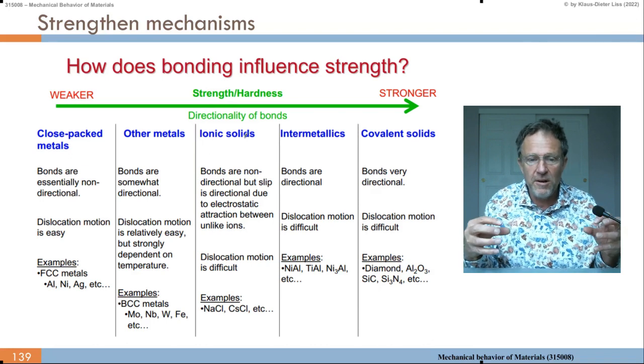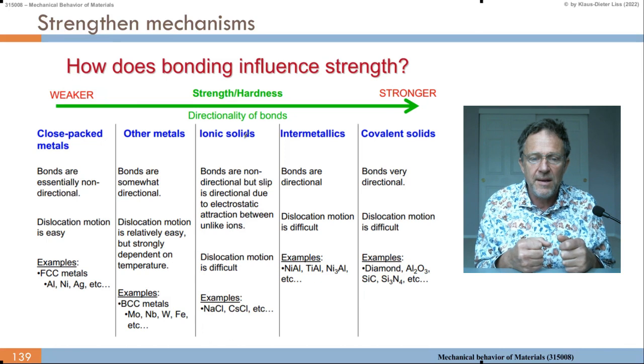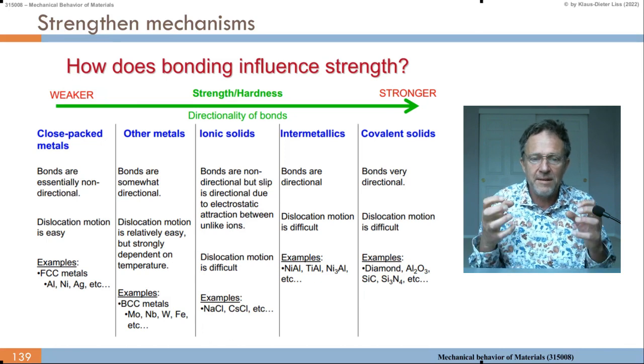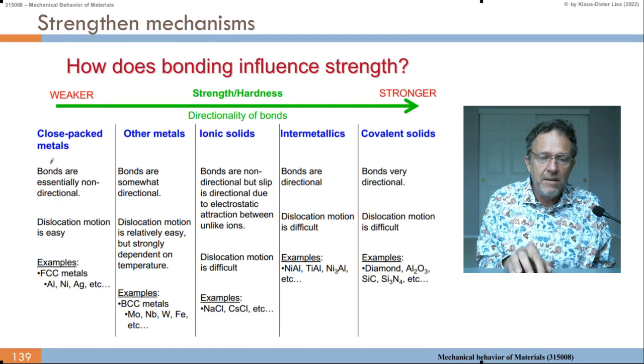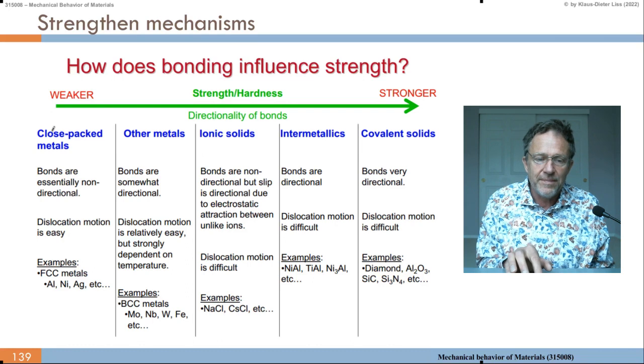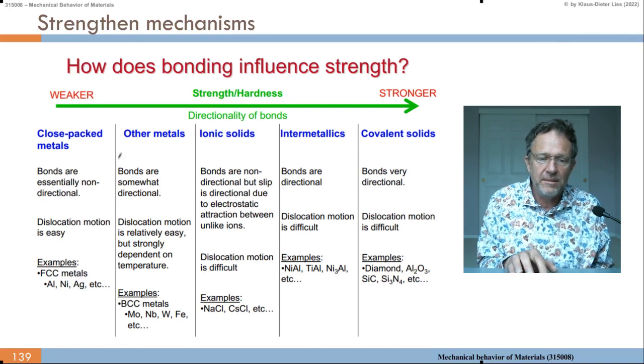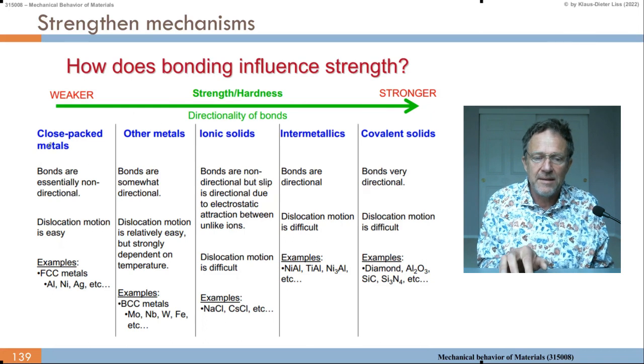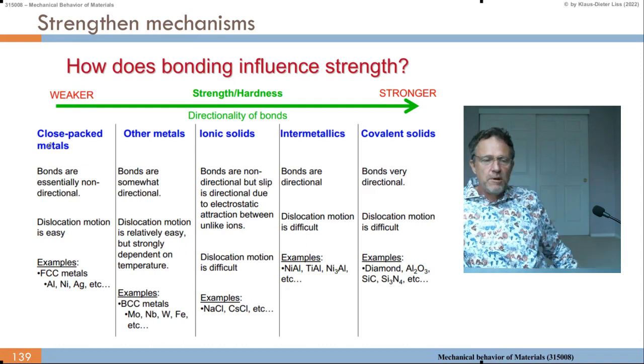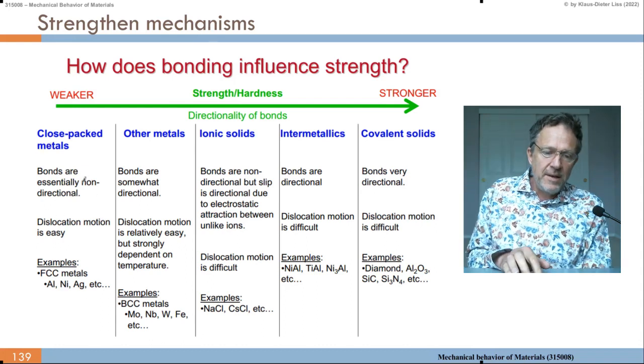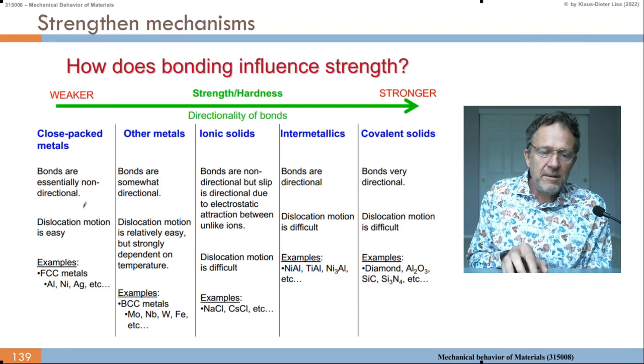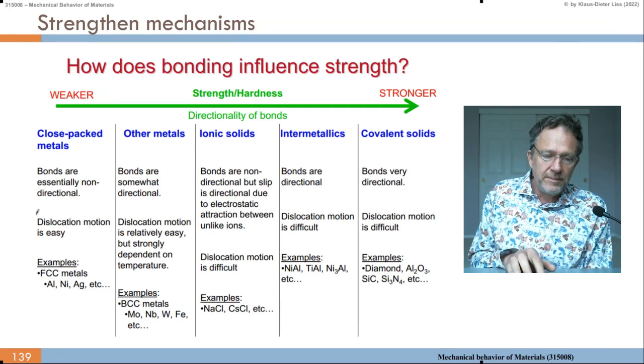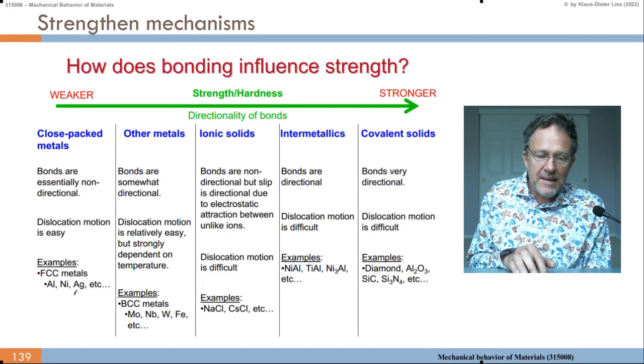So it's not the bond which plays a role, but the electromagnetic repulsion and attraction between dissimilar and similar ions. We have the close-packed metals, which are the weakest, because these are just spheres which are packed together. And then we have the other metals, which may be a little stronger than the close-packed metals, because close-packed is just the spheres. So here, in the close-packed, which is FCC and HCP, hexagonal close-packed and face-centered cubic close-packed, the bonds are essentially non-directional. So the dislocation motion is easy. And here the examples I mentioned already, particularly FCC metals: aluminium, nickel, silver, gold, all your favorite metals.